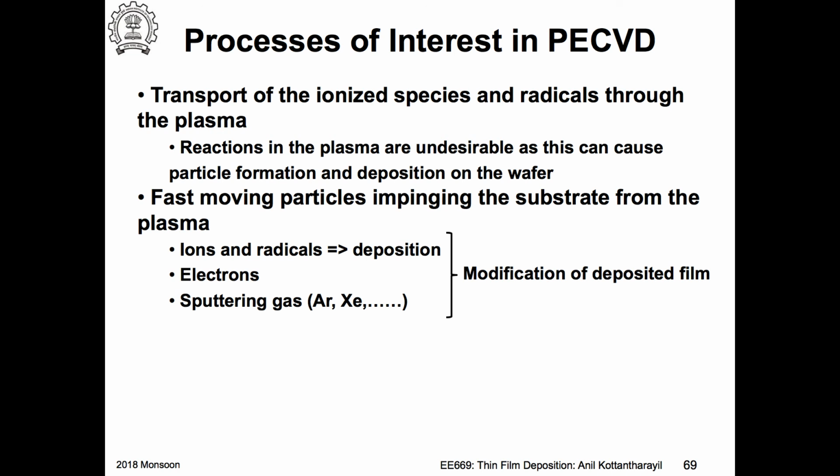Air contains oxygen, so silane would spontaneously burn in oxygen. So I have a problem. A powder of silicon dioxide will be formed, and then that will fall on the wafer. So in practice you need to take care of a lot of things here.